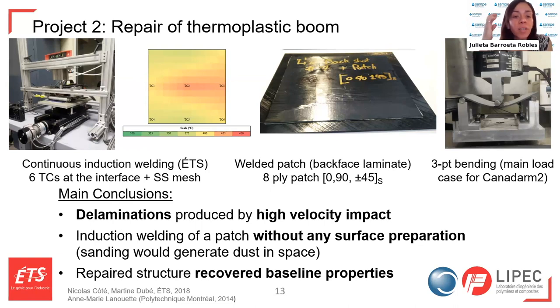Then again, the repair was feasible to be conducted without any surface preparation. And this is ideal in this case because sanding would generate dust in space, and the repair structure recovered the baseline properties.